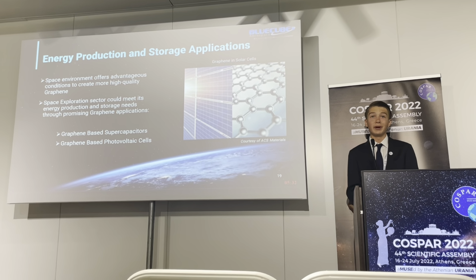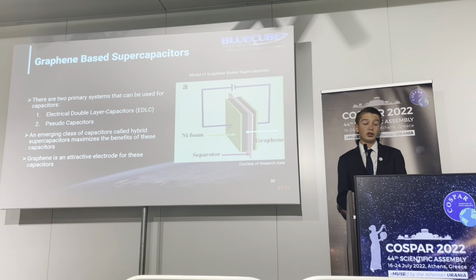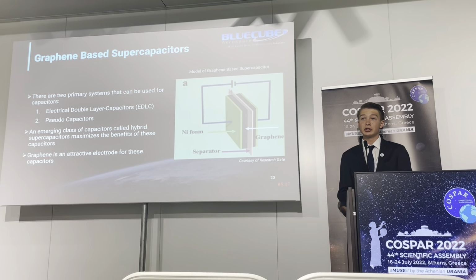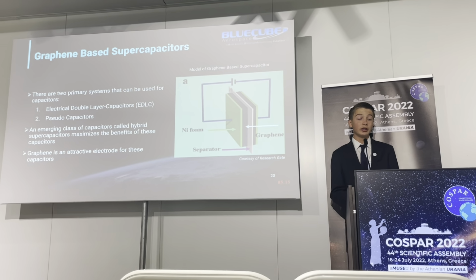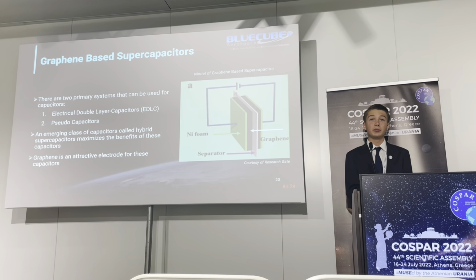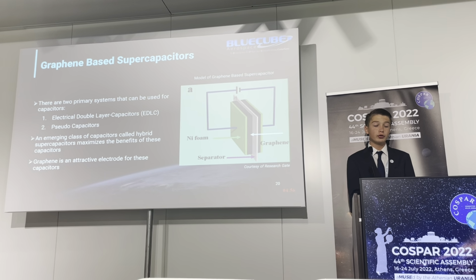First, when thinking about capacitors, there are 2 primary systems that are used for capacitive energy storage. First is electrical double-layer capacitors, EDLCs, and secondly, it's pseudocapacitors. EDLCs have a good life cycle. However, they have a relatively low specific capacitance, whereas pseudocapacitors have a high specific capacitance but poor stability and slow charge discharge rates.